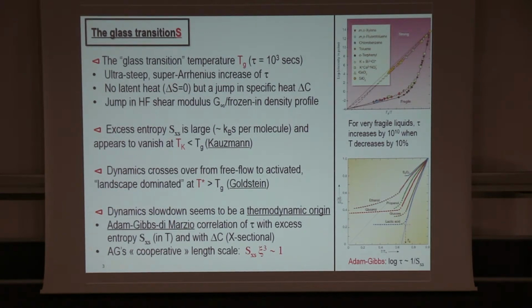And the last thing that I think caught the interest of many of us is that this dynamic slowdown of glasses seems to have a thermodynamic origin, in the sense that there seems to be a correlation between, for example, the entropy and the log of the relaxation time. So the Adam-Gibbs relation is that the log of the relaxation time is just the inverse of this excess entropy that seems to extrapolate to 0 at Tk. This is quite a good empirical correlation, both in temperature and also across different liquids.